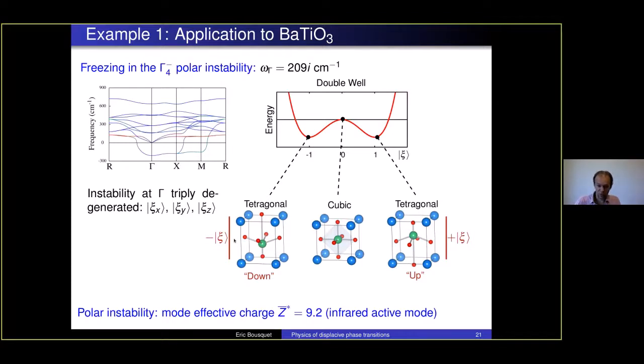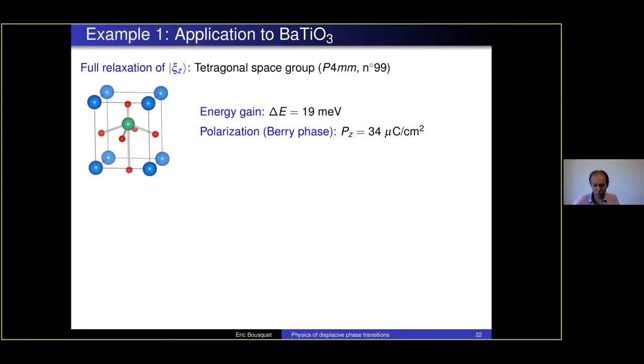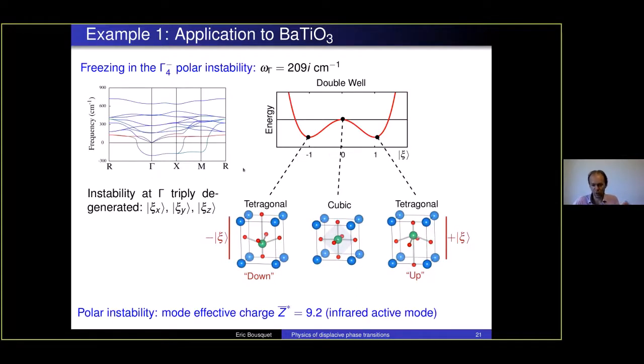So this is the picture with the eigenvector. Now what we need to know is that we have no guarantee that the eigenvector energy landscape will be the final distortion in your crystal. The phonons are calculated here, in the harmonic part of this place. It doesn't mean that when you go away from these points, the harmonic calculation is still valid. So that means that you know what is the path to lower the energy.